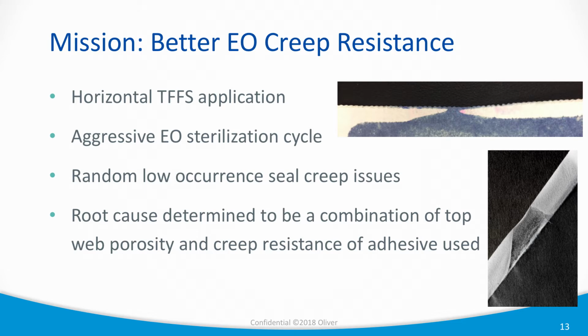You can see the blue dye has leaked through the side seal. So there was a very low occurrence rate. It was hard to track exactly what the root cause was, but it was basically determined to be a combination of the porosity of that top web. So think about breathability. If you have reduced breathability, what does that do? That puts pressure on that lid, creates pillowing, creates stress on the seal, and also the creep resistance of the adhesive that was being used.